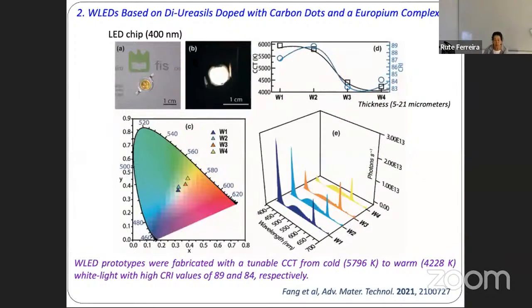And to be able to tune the CCT and the CRI of our prototypes, this time we decided to keep exactly the same concentrations of the europium and of the carbon dots, but we decided to vary the thickness of the layer deposited on top of the bare LED chip. This means that the relative contribution changes, and you can clearly see here in the emission spectrum that the thicker the layer of the hybrid, of course, the lower the contribution from the LED chip. Because of that, we were able to fabricate prototypes with tunable CCT from cold to warm white light with quite interesting CRI values, up to 89.